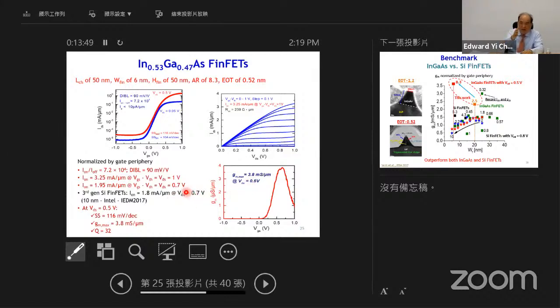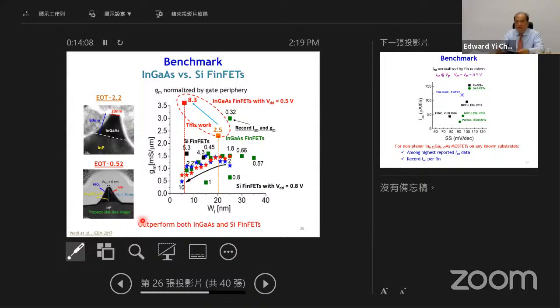Okay, and on the left-hand side, we can see that when the VDS is reduced to 0.5, the SS is still 116 millivolt per decade, and GM is like 3.8 millisiemens per micron. Okay, so this is a very good performance, and probably is the best up to now, if you are talking about the Indium gallium arsenide FinFET. This is an Indium gallium arsenide FinFET with a 0.5 volt. Okay, usually silicon is 1 volt.